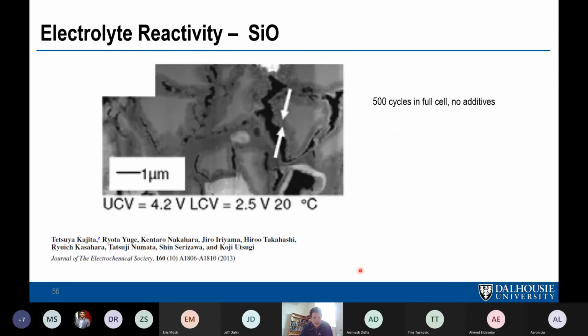And there are papers that have looked at post-mortem cycling of SiO, and it's no different than the alloy. After a lot of cycles, you can still get this surface erosion on top of the particles. The difference with SiO seems to be that this erosion is much slower than a typical alloy material. And it's thought that the reason it's slower is because these are large particles that have a lower surface area, whereas the alloy particles are sub-micron. You can see these particles are a micron or higher. So if you're dealing with sub-micron nanoparticles, this reaction tends to be a lot greater. So that's an advantage of SiO, these low surface area particles slowing down this reaction.